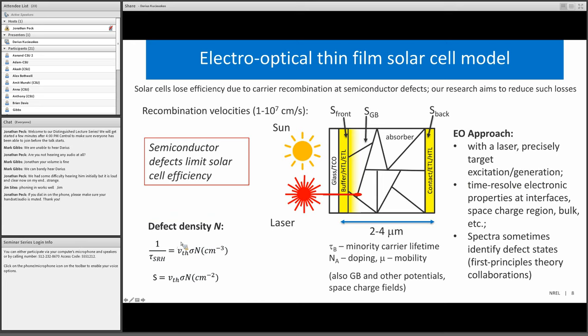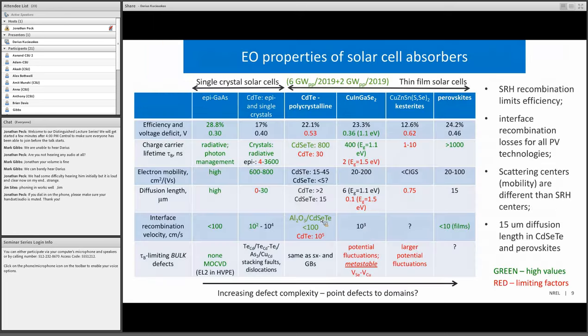So what I'm trying to do in the lab, instead of the sun, is use a laser. I am focusing that laser on a specific area of the solar cell, such as the grain boundary or the interface, and recording an optical response, and from that response determining the defect properties in the solar cell. This table summarizes results of many measurements. It is not meant to be comprehensive. These are just measurements that we've done in our laboratory.